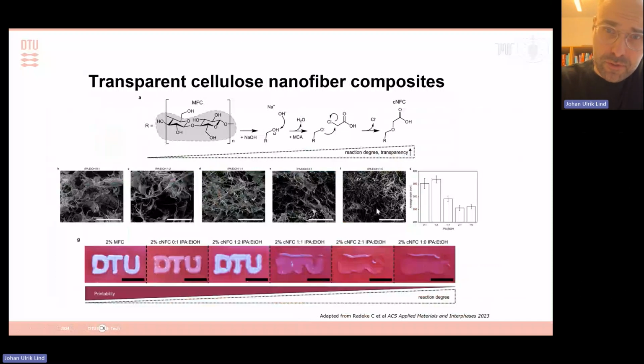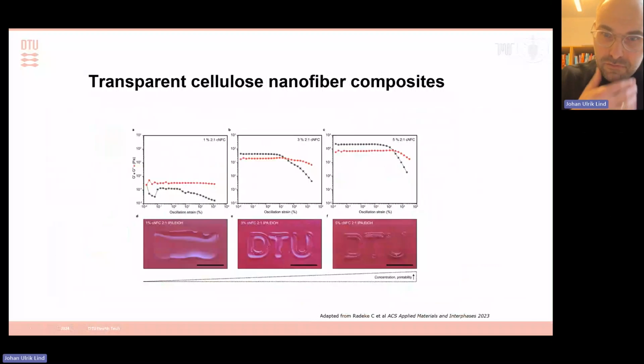We found that to be more robust. And what you can see is that the fibers become smaller, more dispersible, and more transparent, but obviously they are also not as good as print material. So luckily you can fix that by playing with concentration.